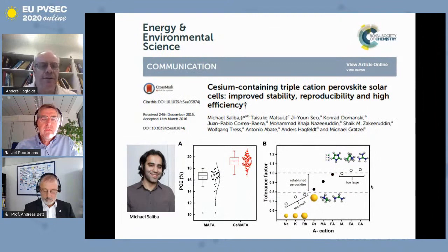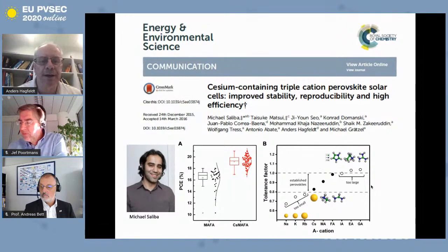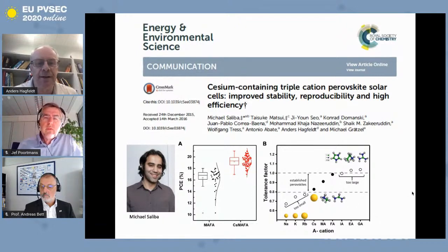What has made this efficiency possible to a lot of extent is the strategy of compositional engineering, where you work on the A site, the cation, you work on the halides and try to find the optimal composition to get the highest quality possible perovskite formation. And from us, this strategy was very much taking off by what we call the triple cation recipe, which we worked with some years back. And you can see here in the efficiency chart, when we compare the double cation to the triple cation, higher efficiencies and also better reproducibility.